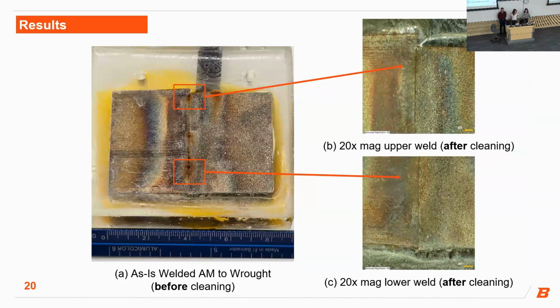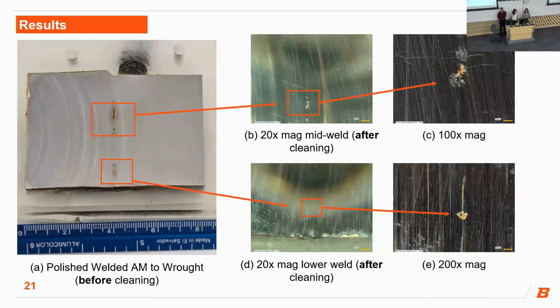Here are some images of our AM welded to wrought as-is sample after the 21 days of immersion. The image on the left shows corrosion products along the weld that confirm the electrochemical activity that we suspected from our EIS data. And the images on the right show what the metal looks like after cleaning. There is some faint discoloration that was not there before. This is our AM welded to wrought polished sample. And again, there's corrosion products along the weld, but there are markings that are more visible after cleaning.